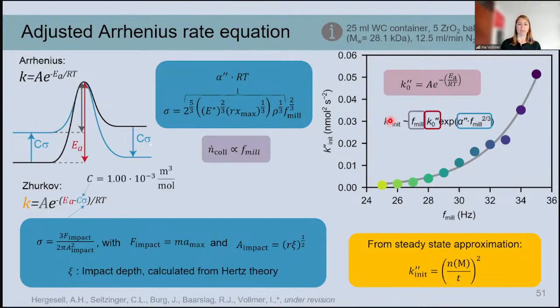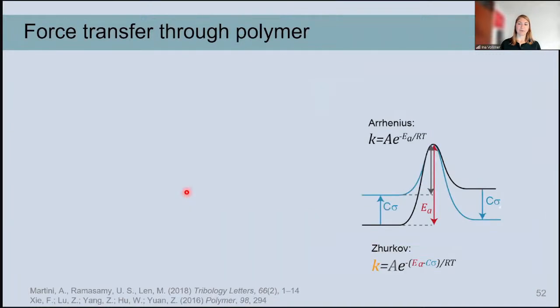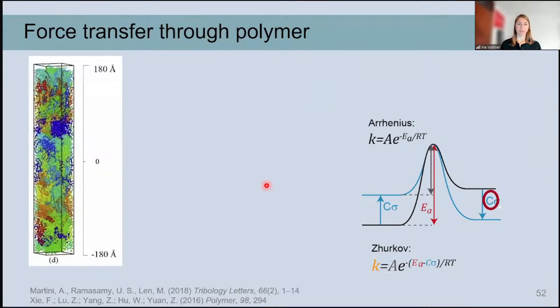And we can then obtain this factor C, this empirical constant. And we try to do the same then. But what about this empirical constant? So this is basically an activation volume, it is often called, and it has to do with how well the force that is applied on a macroscopic piece of polymer actually arrives at the polymer bond.